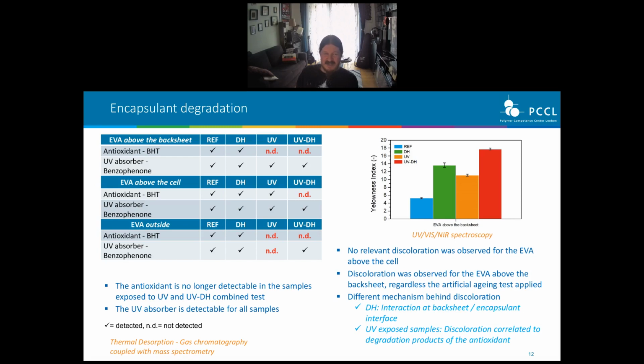So how is this related to the power loss? Let's take a look to the right. You see the yellowness index measured for these different materials, for example above the backsheet, and we see the strongest yellowing after the UV damp heat test, followed by the damp heat test. How was this yellowing formed? The yellowing after the damp heat test is different from that after the UV tests, because the yellowing after the damp heat test is just at the interface of the backsheet and the encapsulant, but not in the EVA encapsulant itself. Therefore, we don't have any power loss.